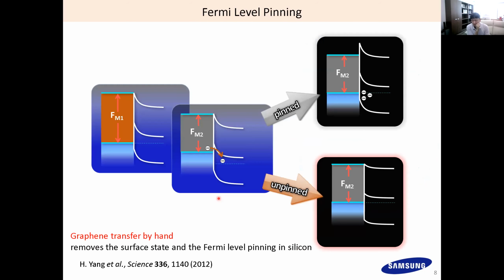But if you think about this van der Waals heterostructure, many people were skeptical. They didn't think it would work because of the phenomenon called Fermi level pinning. As I mentioned, the silicon top surface has broken symmetry. There is no more silicon atom above the top surface, so they make a surface state. Or if we deposit some metals by sputtering or evaporation, they form silicide and again make some surface state, which is an origin for strong Fermi level pinning. So even though we change the work function of the metal, we have Fermi level pinning, and electrons come into the surface state and feel the same Schottky barrier height.